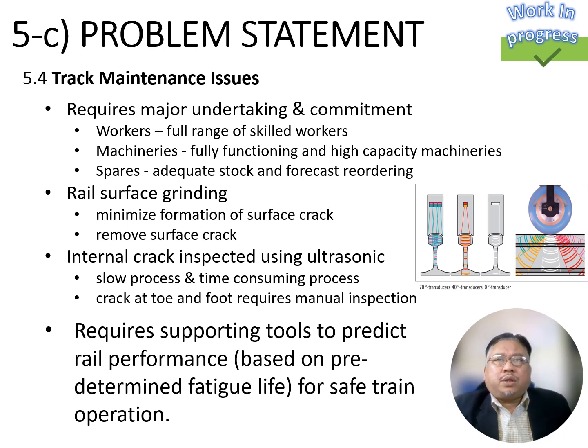Internal crack inspection also requires ultrasonic inspection as mentioned earlier, using 70 degree, 40 degree and 0 degree transducers. These transducers inspect and provide an assessment report of the condition. But at this moment, the current high performance machines operate at 30 to 70 kilometers per hour, and with passenger trains running at 120 kilometers per hour, the inspection train is delayed and mostly operates at night. Therefore, it is very important to have supporting tools to predict rail performance based on predetermined fatigue life or service load conditions to ensure safe train operation.